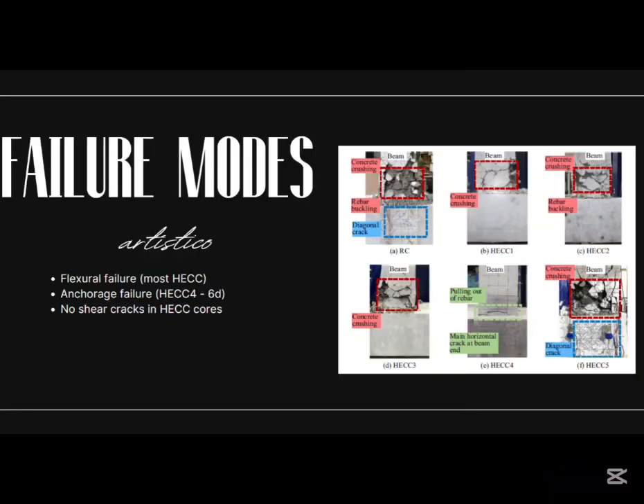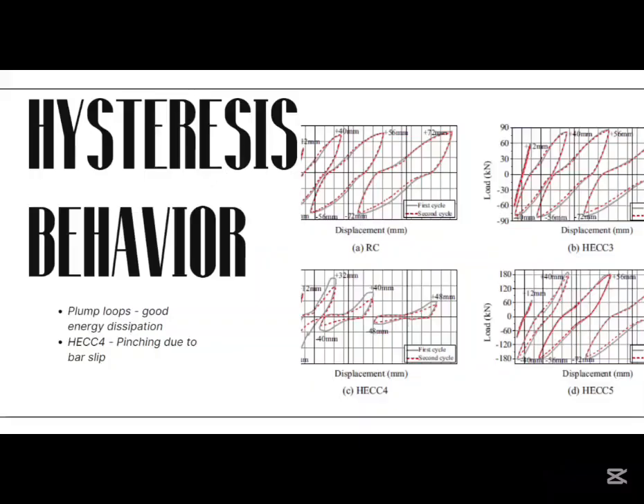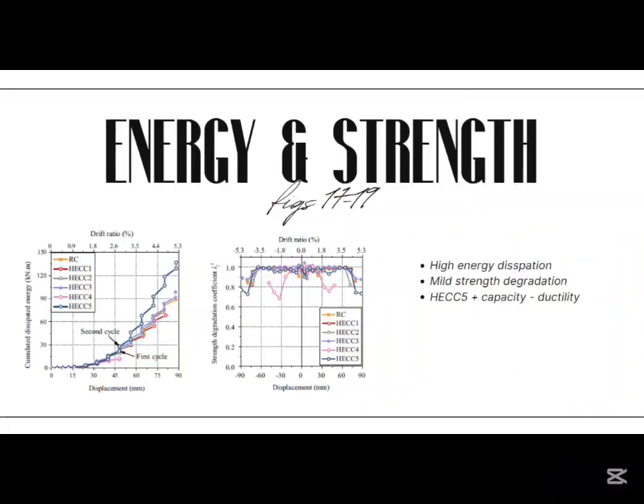Failure modes. Two types of failure were observed. Flexural failure at the beam end occurred. When the specimens were loaded back and forth, the load displacement curves showed plump and stable hysteresis loops for all HECC joints except HECC4. This means they dissipate energy well and maintain strength. And HECC 4 showed pinching caused by bar slip because the anchorage was too short.